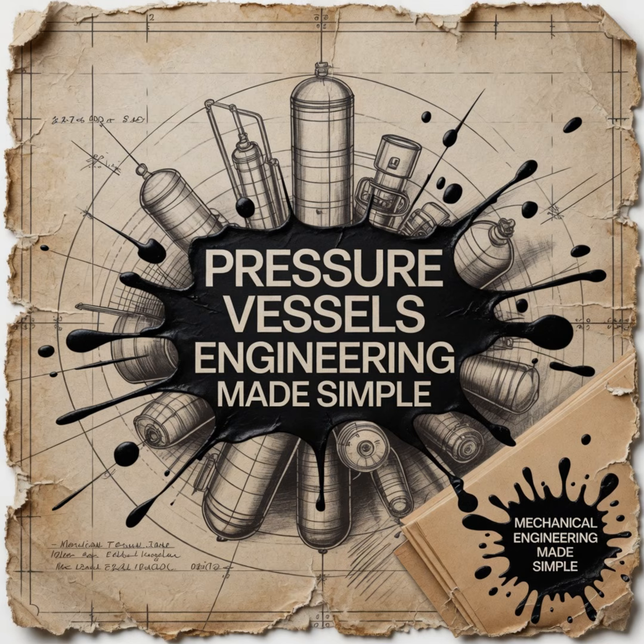And if we throw a corrosive chemical into the mix, the sources mention corrosion fatigue. I'm guessing this is a dual threat situation, like the chemical eats the metal and the pressure changes do the rest. That's exactly the mechanism. It's a localized, synergistic attack. Synergistic meaning they help each other destroy the tank. Unfortunately, yes. The corrosive environment creates tiny little pits on the interior surface of the steel. Okay. Now, normally, a smooth surface distributes stress evenly, but a pit acts as a stress concentrator. It multiplies the local stress at the very bottom of the pit.